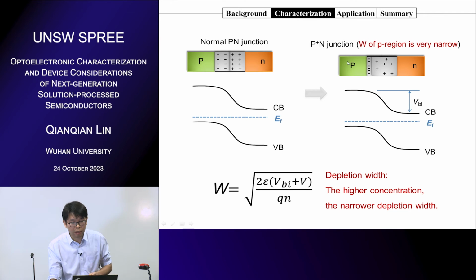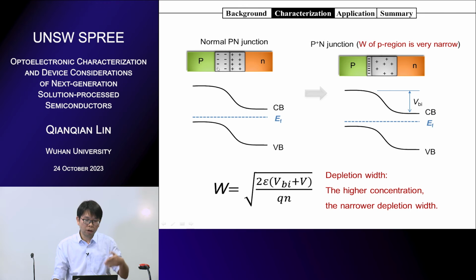Ideally, I want to get rid of holes or get rid of electrons, so I dope one side heavily. So we have a heavily doped p region, then we reduce the width of the p region, and then we measure the capacitance. It is mainly dependent on the n side, so we get the properties mainly of the n-type material. So we normally use a p+n junction for real measurements.